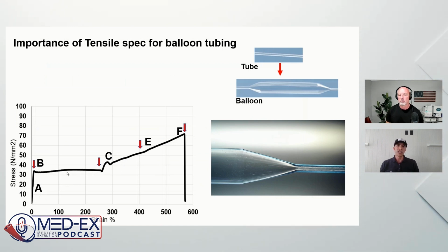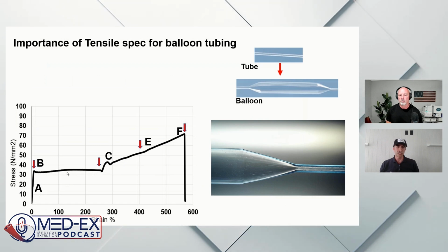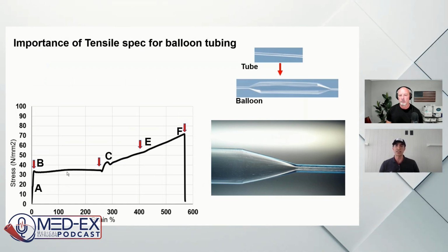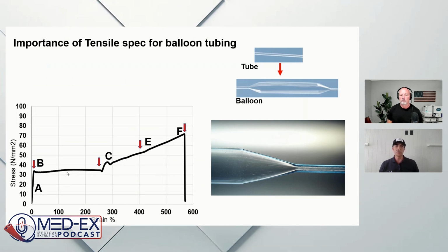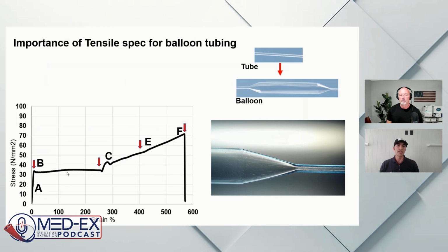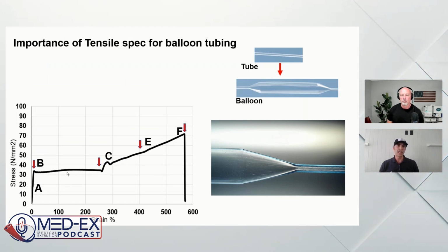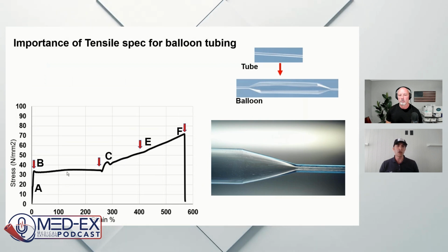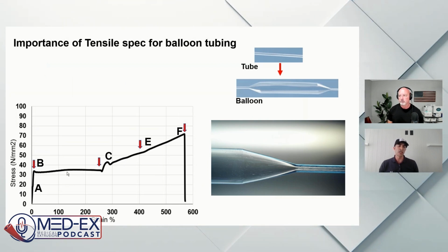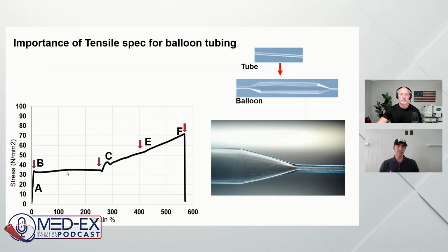The tolerance on that one, it all depends on your material, right, and your process. It's very hard to specify a specific number because there are different tube sizes and there are different tensile curves. Different tube sizes would give you different tensile curves, especially strain at break, right? The higher the thickness, the higher the strain at break would be. So that would be a little bit difficult to specify the tolerance. And as you get to the higher strain at break, your tolerance also gets wider, right? Okay. Because now you're dealing with a higher number in the strain. Gotcha.